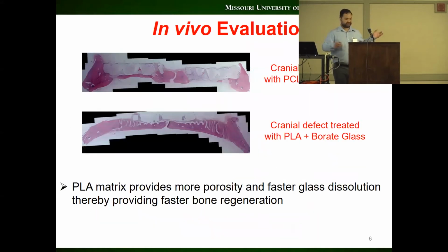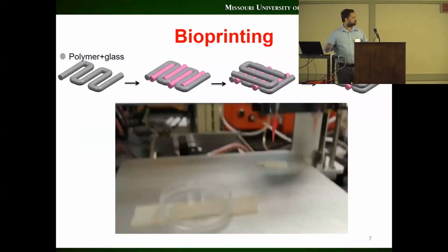So we tested that in animals, and the bottom picture shows a cranial histology of a cranial defect in a rat. You can see that when we use a PLA matrix instead of a PCL matrix, the borate glass dissolves much faster and there is more bone growth.